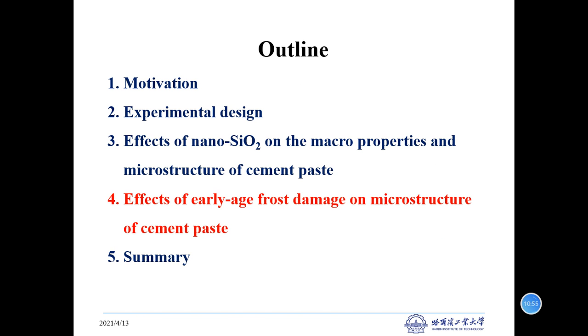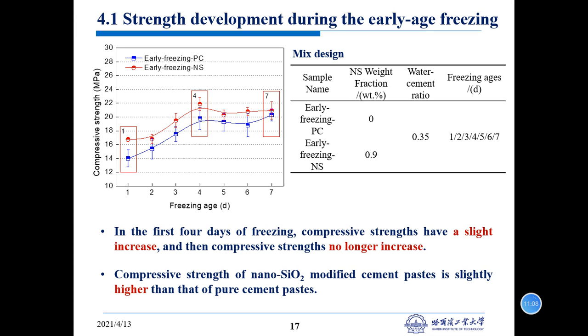After that, we will go on to the fourth part, the effect of early frost damage on the microstructure of cement paste. First, we investigate the strength development during the early frost freezing. We can see like this. In the first 4 days of freezing, compressive strength slightly increased, and then compressive strength no longer increased. And the second one, the compressive strength of the nano-silica modified cement paste is slightly higher than that of the pure cement paste.